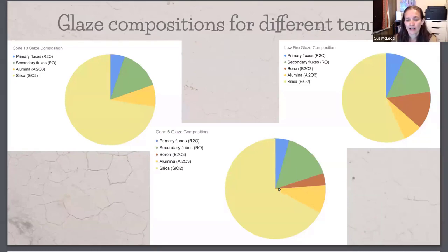So the fluxes stay the same, but now we're replacing some of the silica and alumina, some of the high melting temperature glass formers, with boron, which is a low melting temperature glass former. So we're reducing the silica and alumina to give space to add a little boron to help the glaze melt at cone 6.